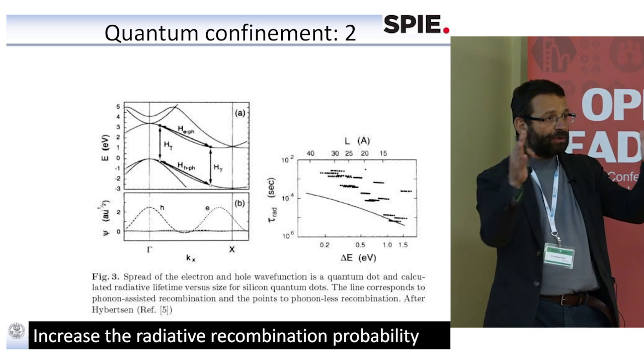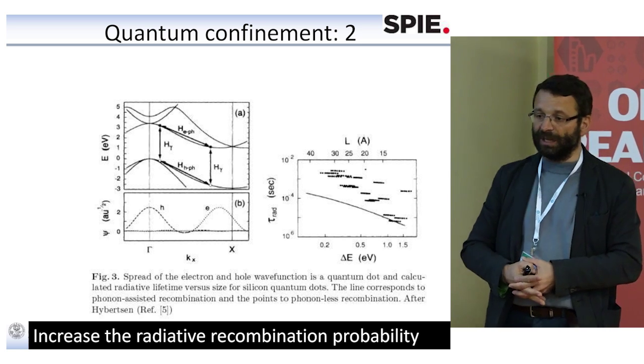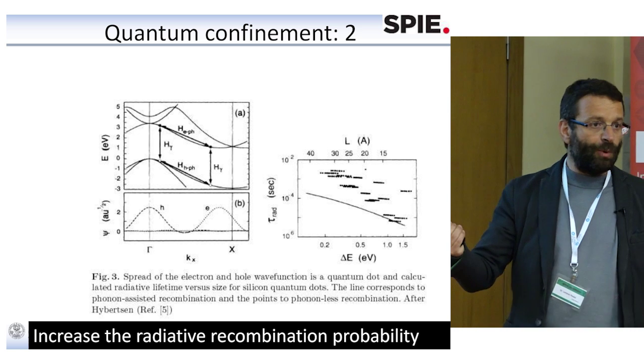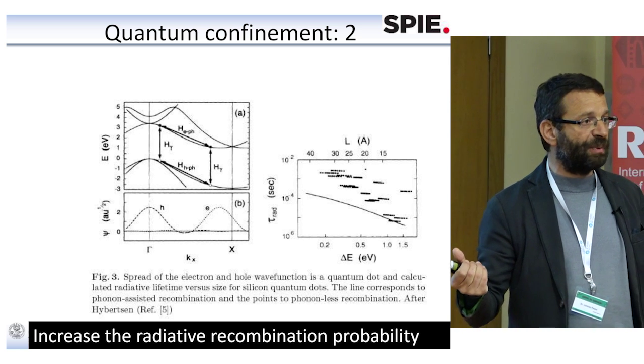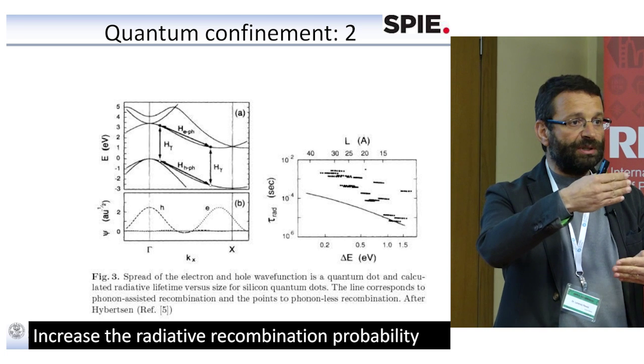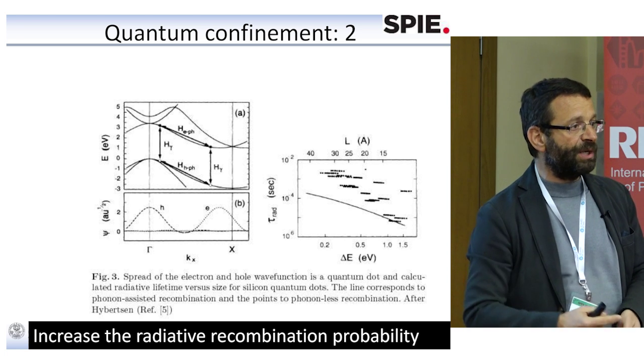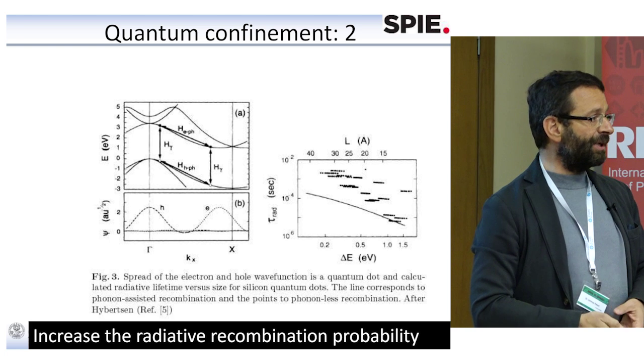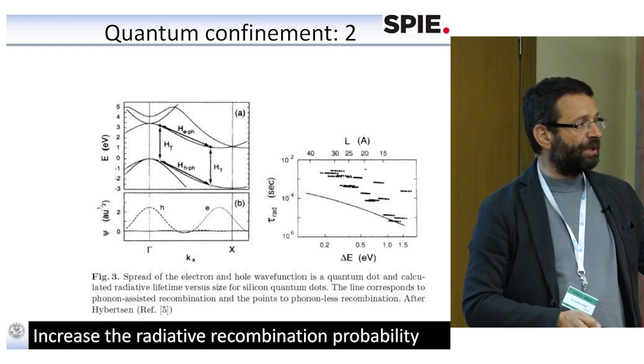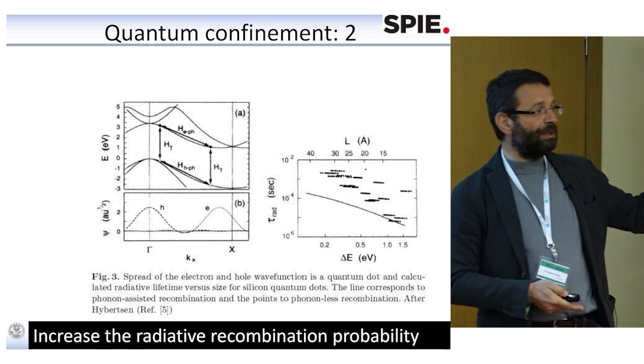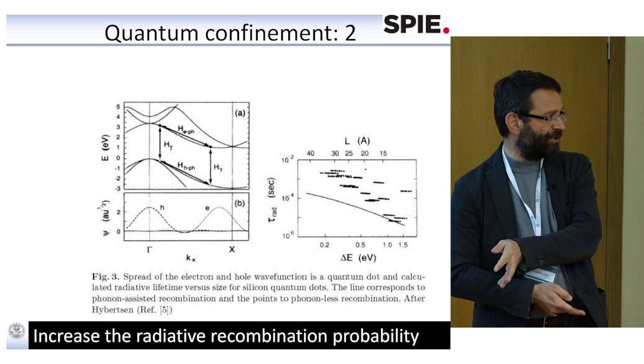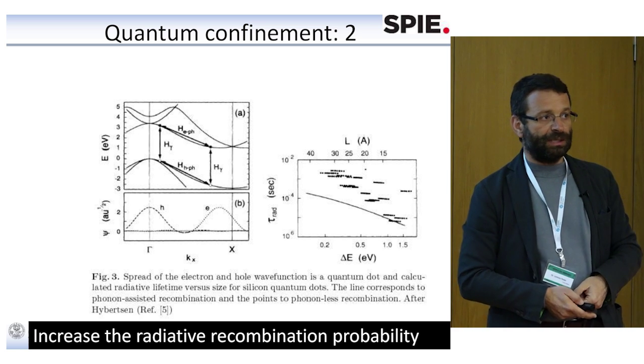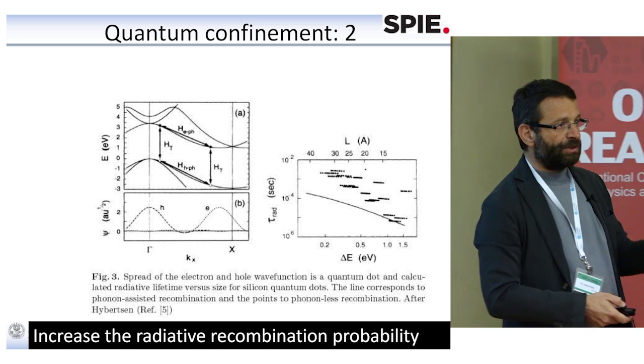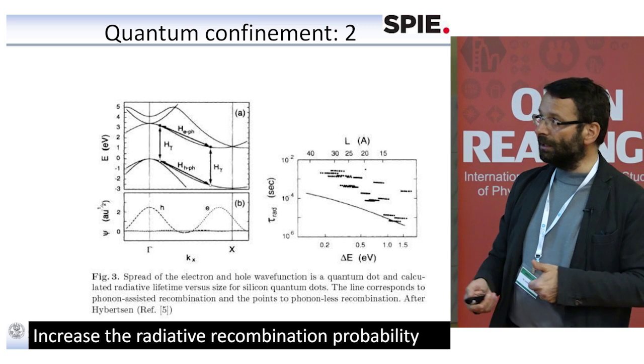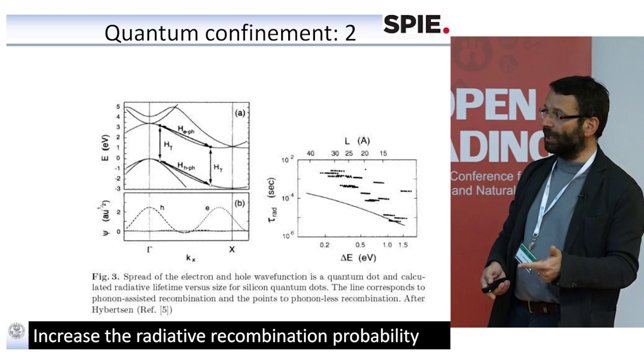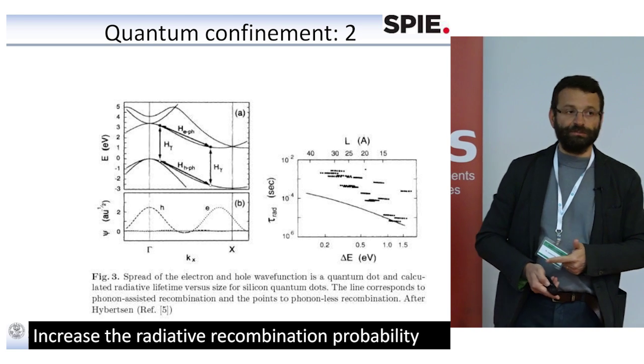So the more you confine the free carriers in space, the larger the widening of the wave function in the K space. So you increase the overlap between the two, and so the radiative recombination probability increases. Now the radiative lifetime moves from the 10 milliseconds typical of silicon down to the microseconds typical of silicon nanocrystals. So you get a widening in the transition energy and an increase in the radiative recombination probability.